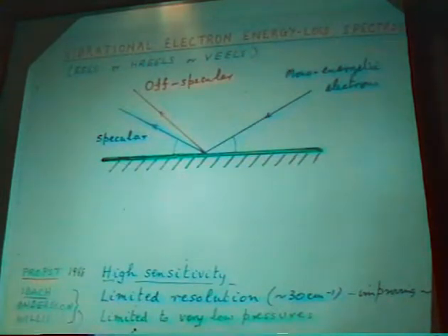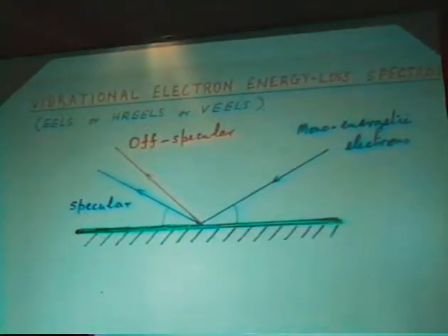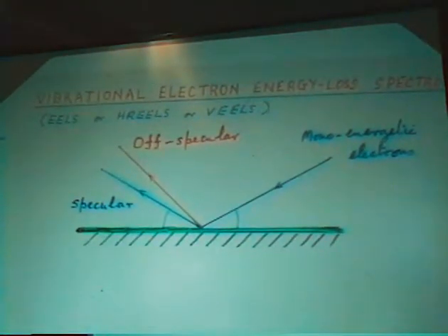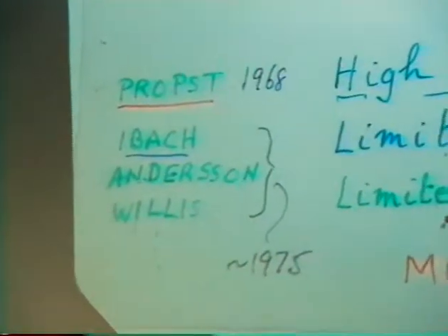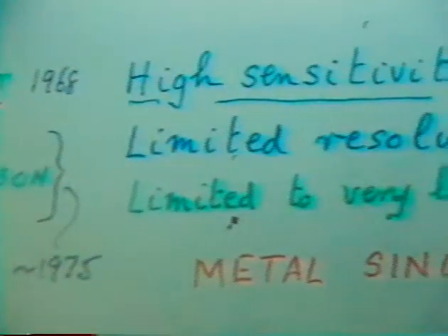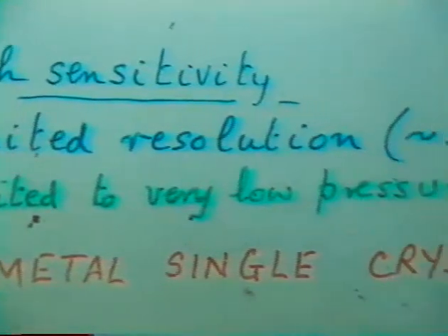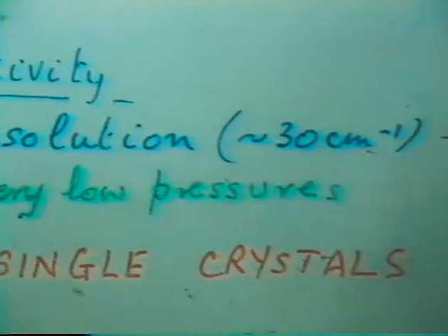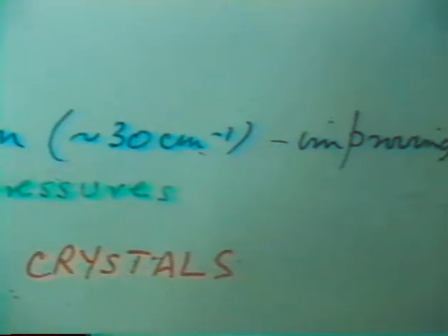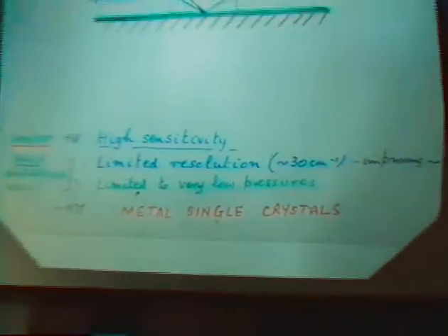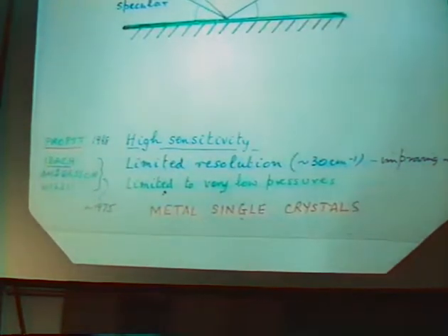Electron energy loss spectroscopy is analogous in some ways to Raman spectroscopy. Raman could be photon energy loss spectroscopy. You bring mono-energetic electrons into the surface and bounce them off the surface. They transfer some of their energy to excite the vibrations in the monolayer, and therefore those electrons leave the surface with reduced energy, and you measure that energy loss.